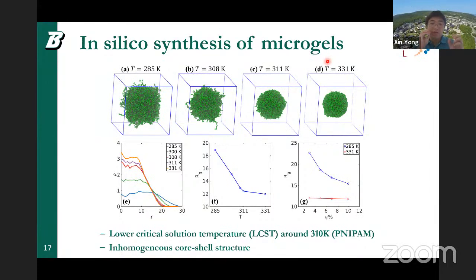We first initialize and equilibrate a droplet, which is a mixture of initiator, monomer, cross-linkers, and solvent. Then we have an in silico reaction which connects these beads together. Therefore, the cross-linkers are randomized, and the structure is also highly inhomogeneous. But we believe this better represents the experimental condition, because in experiments the microgel is made by polymerizing in an emulsion droplet. So the concentration only influences how many cross-linker beads we put into the system, which in turn influences the average strand length, but the network itself is inhomogeneous.